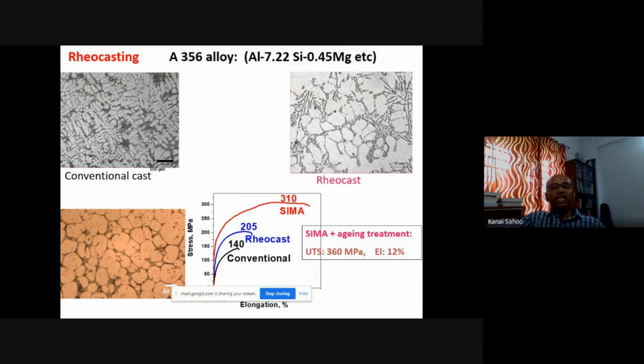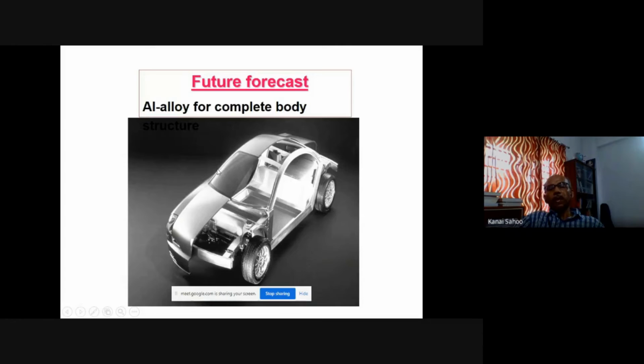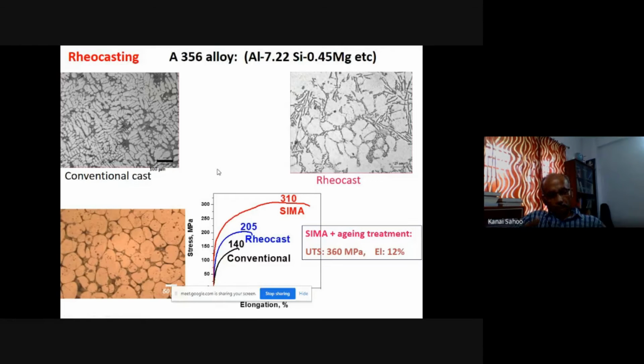For example, the same alloy I just took: Rheo casting, conventional casting, and then this is the SIMA treatment, so that you can increase your strength and ductility both. With SIMA plus aging, you can improve your properties further. But this SIMA technique is rolled, and then heat treatment is applied to the very thin section of the casting.